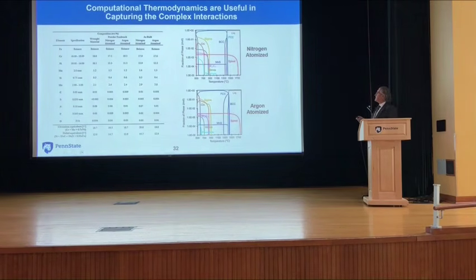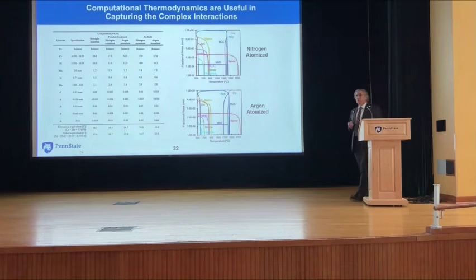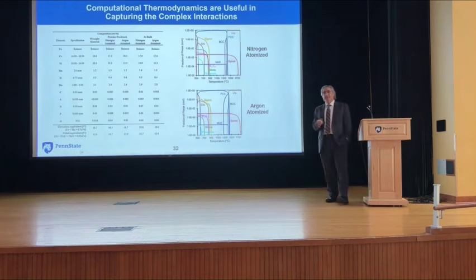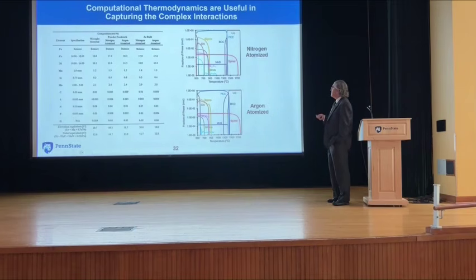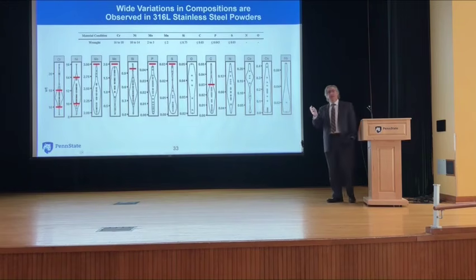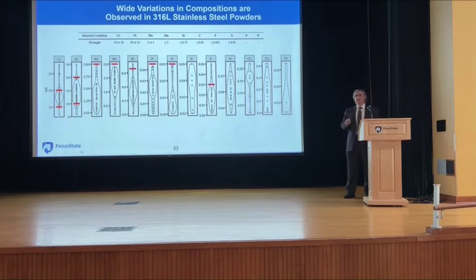So that iron-carbon phase diagram that looks so simple, if we look, these are for 316L stainless steel, and the difference here is a slight difference in the amount of nitrogen. And what we start seeing is sigma phase, which is not something you want. If you're going to have corrosion problems in an austenitic or duplex stainless steel, sigma phase is going to be somewhere in it. And it just shows you how complex, even at small amounts, these different secondary phases can play a role in leading to defects, leading to failures, and it's always the failures you don't expect.